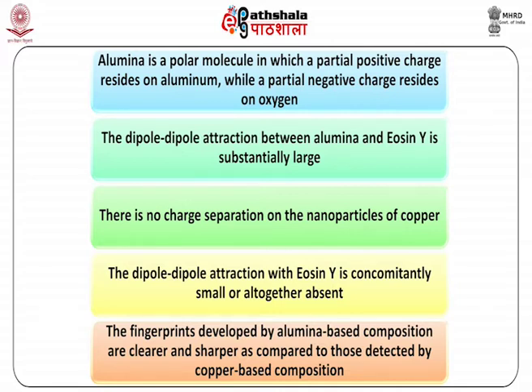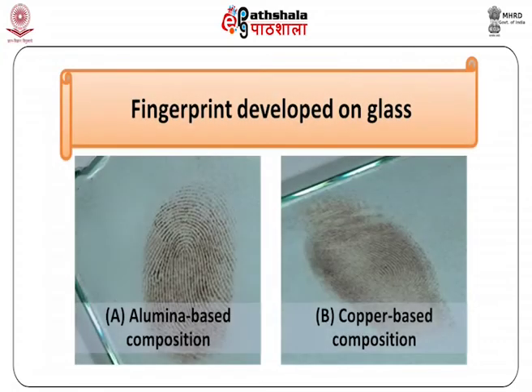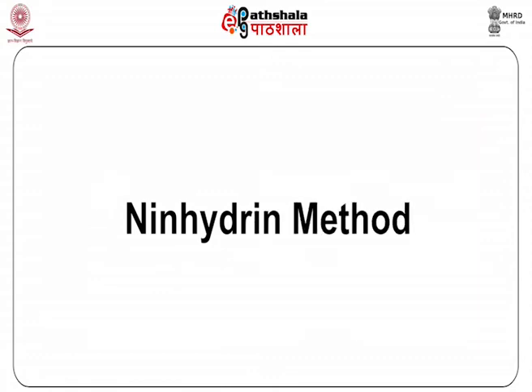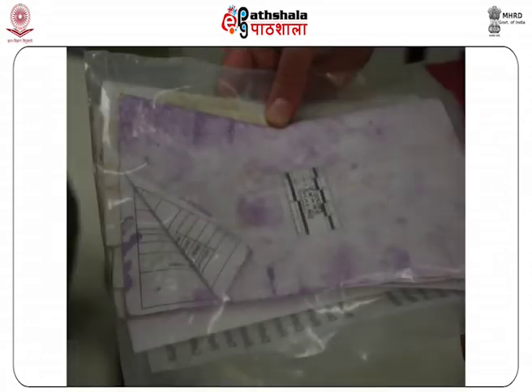For this reason, the fingerprints developed by alumina-based composition are clearer and sharper as compared to those detected by copper-based composition. A comparison of fingerprints developed on glass by alumina containing formulation and copper containing formulation supports this assertion. Another useful method is the Ninhydrin method. Ninhydrin treatment is one of the premier techniques for development of latent prints on porous surfaces such as paper.